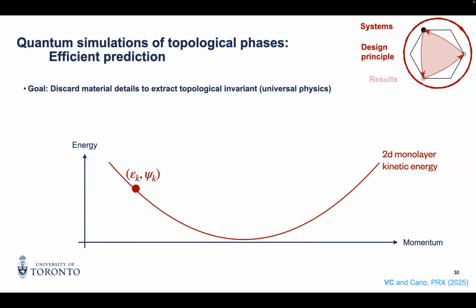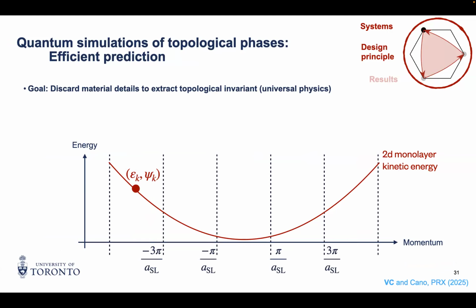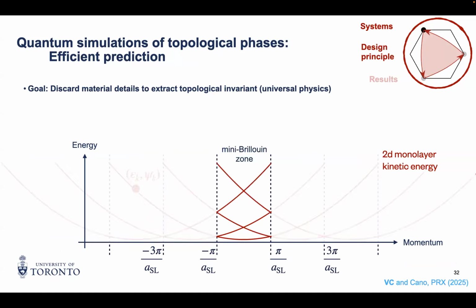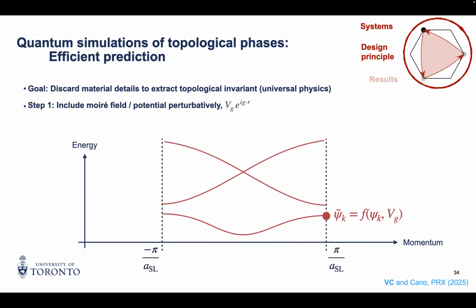So what happens in that case is quite simple. You have the 2D monolayer that you put on top of your patterned dielectric. The dielectric introduces a superlattice. The superlattice period is large, so the Moiré Brillouin zone is small. So you fold all of the dispersion into that new Brillouin zone, so the inequivalent crystal momenta, and the harmonics of the superlattice potential are going to open the gap at the edges of your Brillouin zone. Right? And all you have to remember for the sake of this talk is that you can obtain the gap at the edges of the Brillouin zone and the wave function at the edges of the Brillouin zone with perturbation theory.